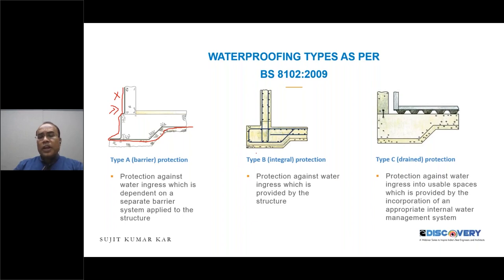Now, if we are talking about type B waterproofing, where we are adding certain chemicals, certain integral waterproofing compounds to the concrete structure, so that the porosity of the concrete minimizes and the density of the concrete increases, which will lead to poor penetration of water inside the concrete structures. So all kinds of integral waterproofing compounds or pore blockers work in this pore blocking mechanism.